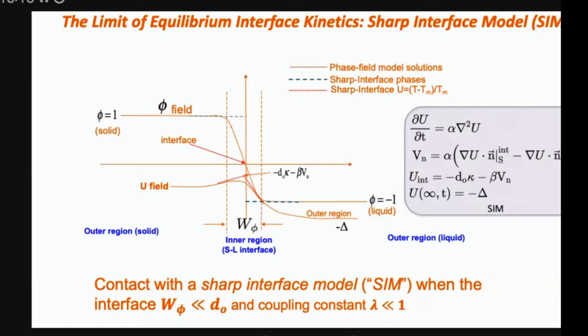If you were to do an analysis of this model, when the interface and the coupling function become really small, what you'd find is that your model evolves in such a way that the interface is roughly always in local equilibrium, where your interface is essentially at the equilibrium value, corrected possibly by a curvature effect. And there's supposed to be some kinetic effect, but it's very manageable.